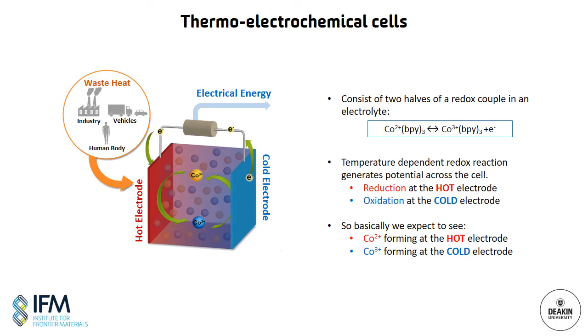So what are thermo-electrochemical cells or thermocells? Well, they consist of two parallel metal electrodes and an electrolyte that contains a redox active species. And what happens is we get redox reactions occurring within the electrolyte, and the equilibrium of this redox reaction will depend on temperature. So the balance at each electrode is different, and this leads to transfer of electrons through the external load. So what we get typically is reduction occurring at the hot electrode, oxidation occurring at the cold electrode, and a continuous circulation of the different redox species. So this basically allows the devices to generate continuous electricity under the application of a thermal gradient.